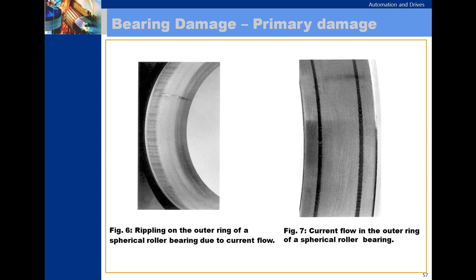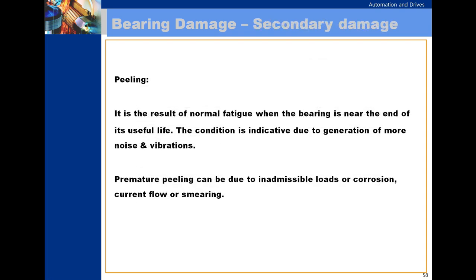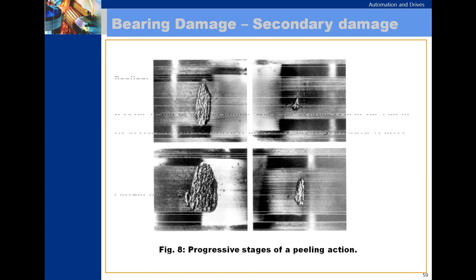The rippling on the outer ring of the spherical roller bearing is due to current flow. You can see in the picture clearly the current flow damage in the outer ring of the spherical roller bearing. Peeling is a result of normal fatigue when the bearing is near the end of its useful life. The condition is indicated by generation of more noise and vibration. Premature peeling can be due to inadmissible loads, corrosion, current flow or smearing.